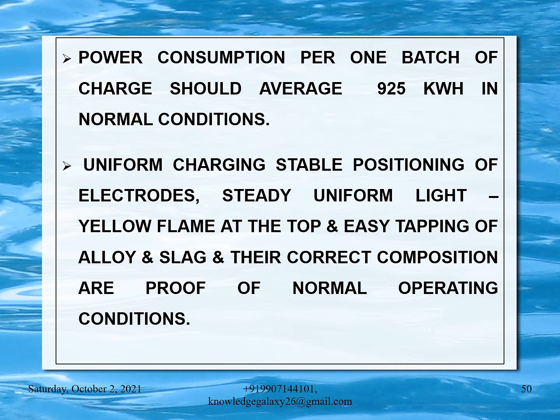In the smelting of ferrochrome, there may occur sulfur waste, and because of it, the process is conducted with a hot furnace top to ensure the evaporation of sulfur. High sulfur fine coke shouldn't be used. Power consumption per one batch of charge should average 925 kWh in normal conditions. Uniform charging, stable positioning of electrodes, steady, uniform, light yellow flame at the top, and easy tapping of alloy and slag and their correct composition are proof of normal operating conditions.